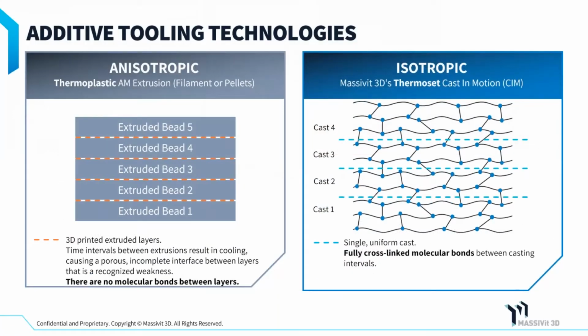Here's a graphic to explain why it becomes isotropic. On the left, if you're extruding a thermoplastic, you have what I call a barrier or a weak spot, which is between the extruding layers. That's always going to be a weak spot. Even in some of the industrial 3D printers that can extrude thermoplastic and have a heated build chamber, the Z direction is much weaker. And if they're putting in strengthening agents like glass fiber or carbon fiber, it's only in the XY. As you're extruding it, the fibers line up, and nothing happens in the Z direction. With our material, it all blends together. You're seeing it cross-linking through the different pour layers, like cast 1, cast 2, cast 3, and they're all blending together.